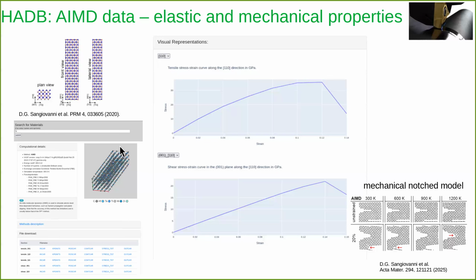What we are doing here is taking the structures and pulling them along the Z direction, or shearing them accordingly, depending on what we would like to know. Again, we store all the input information, and also some of the output files which are cleaned so that they won't be so big, and then the stress-strain curves, which are also represented in different directions. Here you see for this particular case an alloy, a hafnium tantalum titanium zirconium carbide, and its stress-strain curve along the 110 direction. So if you take the shear stress-strain curve in the 001 plane along the 110 direction in gigapascal, then you will see the signal. That's it.